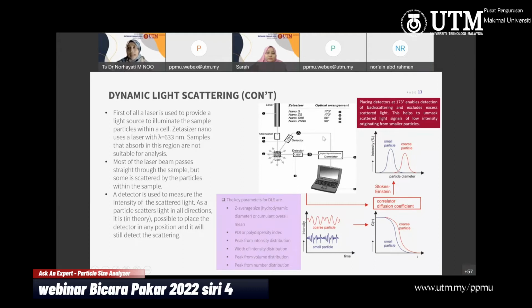For the one in UPM, they use the Nano ZS. As a default, the detector is set at 173 degrees. What this means is that the laser comes to the sample, and there is an attenuator that controls the power of the laser that reaches the sample. Then it goes to the cell, which holds your sample, and your sample scatters the light, and the detector here, which is the A, is at 173 degrees.